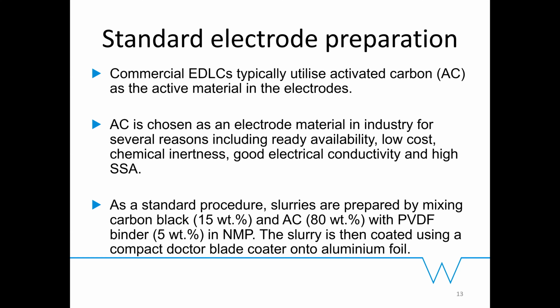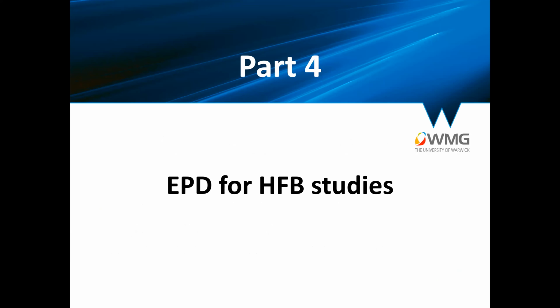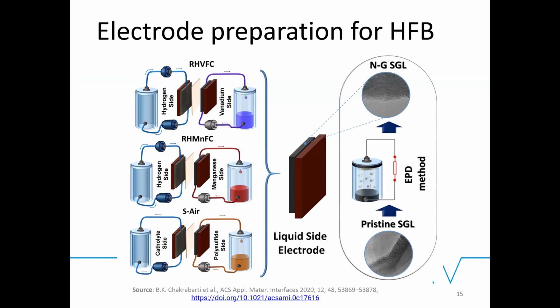So moving on to my research, how did I use electrophoretic deposition to improve hybrid hydrogen flow battery studies? In this cartoon, I'm showing, like I mentioned in the early part of my talk, that I was using a classical method of EPD, electrophoretic deposition, where you have vertical electrodes. But in this case, for the flow battery experiments, I used a horizontal setup. So the working electrode is kept at the top here, and the counter electrode is at the bottom. And then by applying electrical voltage, trying to minimize the amount of current generated for the EPD, to do a controlled migration of the graphene to the top of the electrode, so that we don't have clustering of the graphene afterwards to form graphite layers.